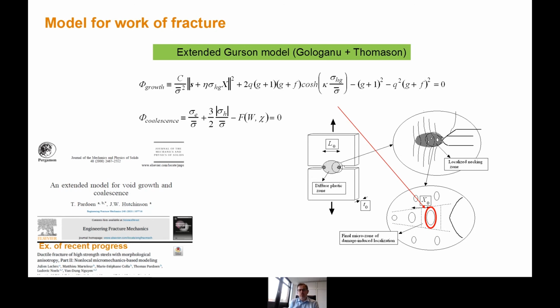And once again, the work of necking per unit area evolves proportionally with thickness. For the gamma zero term, this part is more complicated, because we need a damage model to calculate the work spent to nucleate, grow, and coalesce voids in a zone which is undergoing a stress state that is representative of the stress state at the tip of a crack in a thin sheet. Every word I said is important.